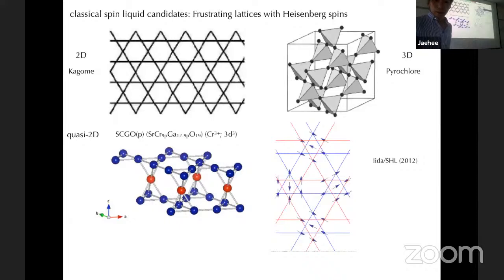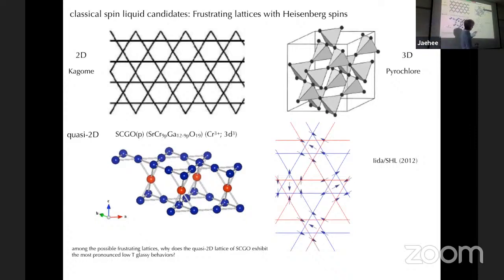On the other hand, this SCGO case. One set of classical ground states is shown here, a top view of this lattice. The red lines are the one kagome lattice. Blue lines are the other kagome lattice below. And the center of the two triangles is this triangular lattice here. The classical ground state is when every tetrahedron has zero net moment. You can see the one red triangle at the center, they form one tetrahedron.